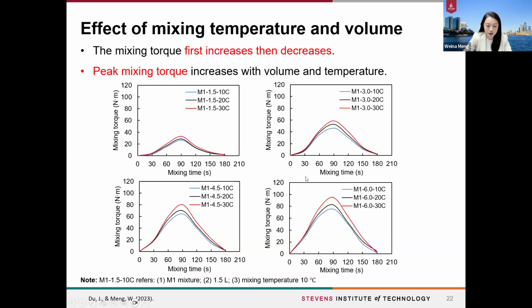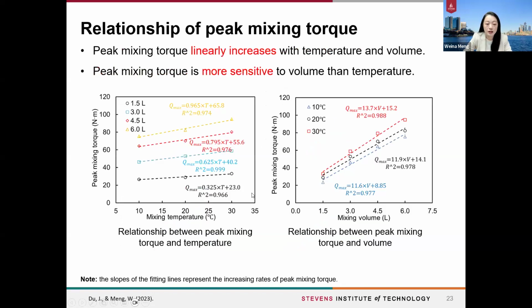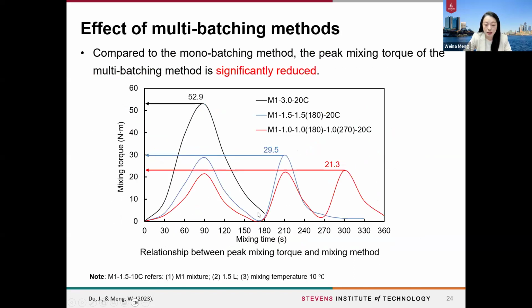So from our results, we find that both the temperature and the volumes, so increase of the volume and temperature, significantly increase the mixing torque. And the peak mixing torque is more sensitive to volume than the temperature, as we can see in this analysis results. And doing the multi-batching can effectively reduce the peak mixing torque.